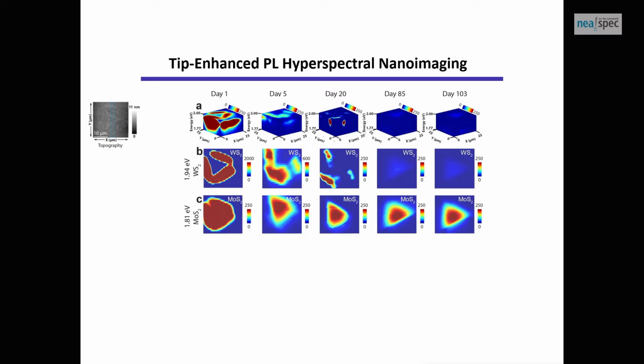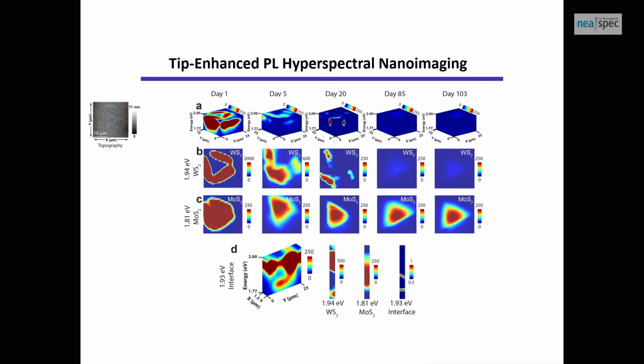You notice that the PL on WS2 changes. It starts to concentrate on the edges and then eventually disappears, whereas in the MoS2 it changes, but not dramatically like WS2. When I first saw this, I was like, wow, this is cool, right? Something is going on. You can also look at the interface by subtraction of signal. You can isolate the interface region as well, which is 100 nanometers thick in PL emission, which is quite nice.